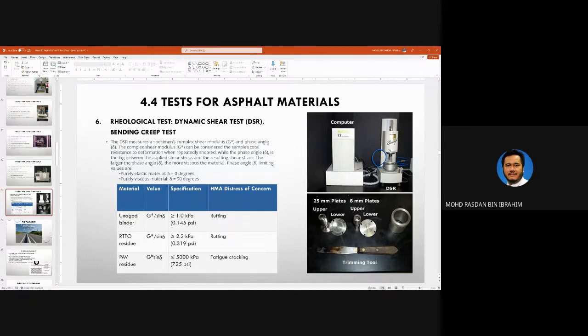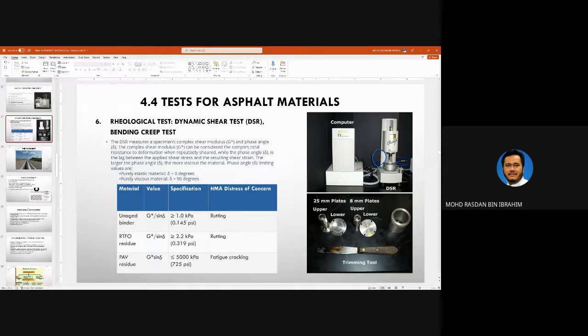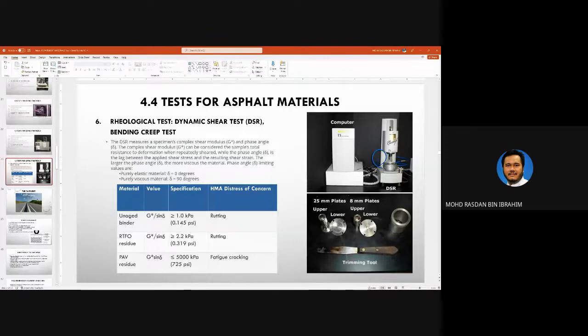The most common variable that we measure is the complex shear modulus G star, and also the phase angle delta. So it measures the elastic component and the viscous component of the material. It will subject the bitumen to rotating, twisting the sample, and then measure the elasticity and viscosity. So from these two values, the G star and the delta, you can calculate the tendency for the binder to rut or to crack.